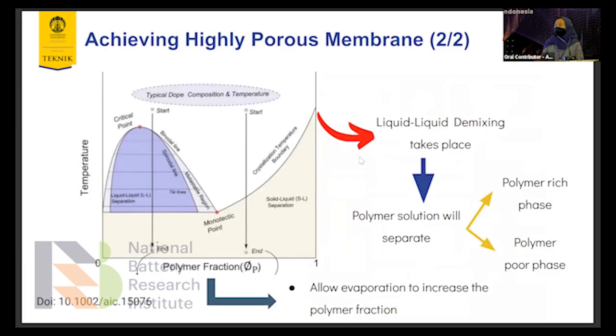So why do we need to vary the evaporation time? The evaporation time relates to the polymer fraction. The shorter the evaporation time, the lower the polymer fraction will be, because there will still be more remaining solvent. And when we increase the evaporation time, there will be a higher polymer fraction. Why do we need to maintain the polymer fraction? Because when we quench the polymer into the coagulation bath, there will be a difference in its pore structure. If it's in the lower polymer fraction, there will be a phase separation.